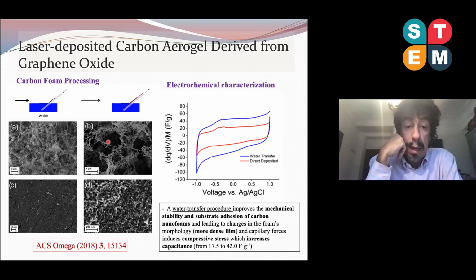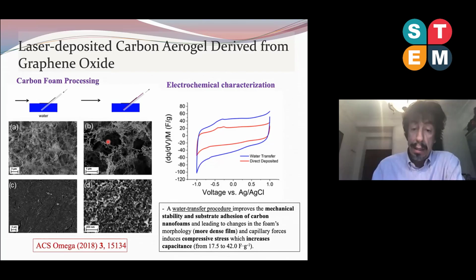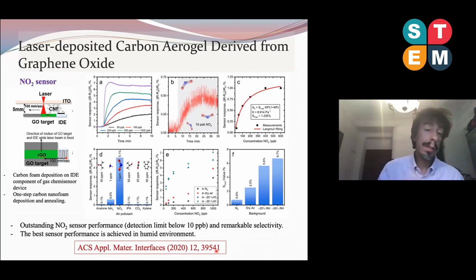And this material actually presents nice conductivity and nice capacitance. So by doing this water transfer process, we increased the capacitance of these materials from 17 to 42 farads per gram. And these materials, if deposited on interdigitated electrodes, can provide remarkable nitrogen dioxide, NO2, sensor capabilities. This is interesting because we observed a very low detection limit, below 10 parts per billion, and very remarkable selectivity when compared with other contaminants, pollutants.